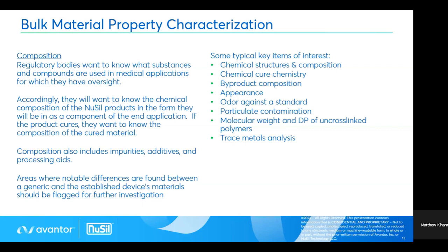Byproduct and residual composition from the curing mechanism and processing, appearance of the cured and uncured material, odor against the standard, particulate contamination of the cured and uncured material, the molecular weight and degree of polymerization of the uncross-linked polymers in uncured form, and trace metal analysis. Again, multiple ASTM methods, ISO standards, and USP standards exist to cover these characterizations, either generically or for specific end uses. Next slide, please.